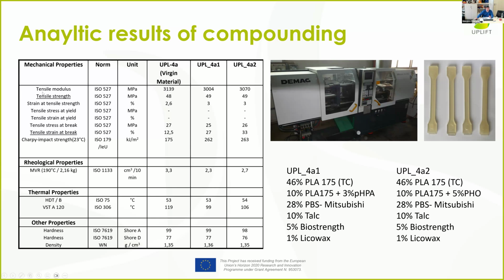One of the most interesting analytic results here is the Young's modulus. We see that it lost a little bit of its stiffness. It's becoming more flexible. The second thing is the tensile strain at break. We will see that this material is more stretchable. It's more flexible. And so for the flat extrusion, this is a very, very good sign because you don't want your material to be too stiff.